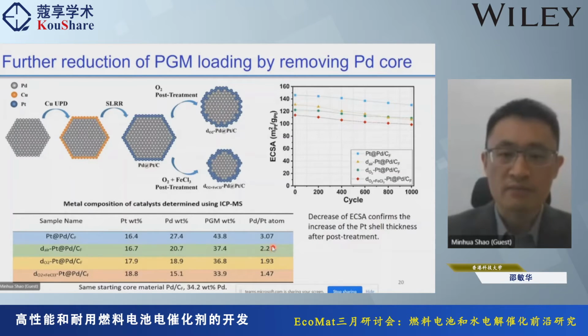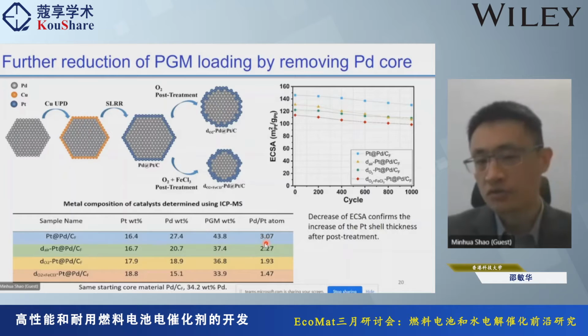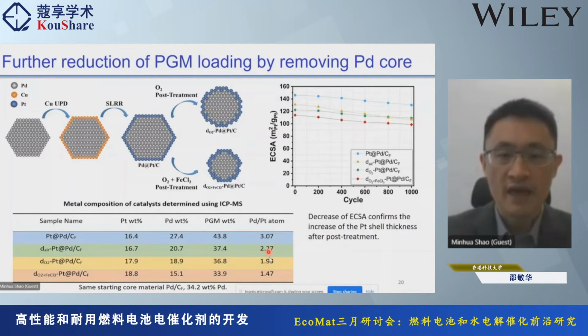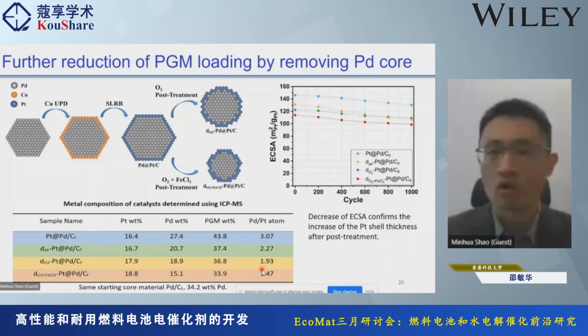So air is a milder dissolution condition. The palladium to platinum atom ratio changes from 3 to 2.3. And if you add oxygen instead of air, it is further reduced to about 1.9. If you add the iron chloride, it decreases to 1.5. Right? So basically, you can remove a lot of the palladium inside the core.